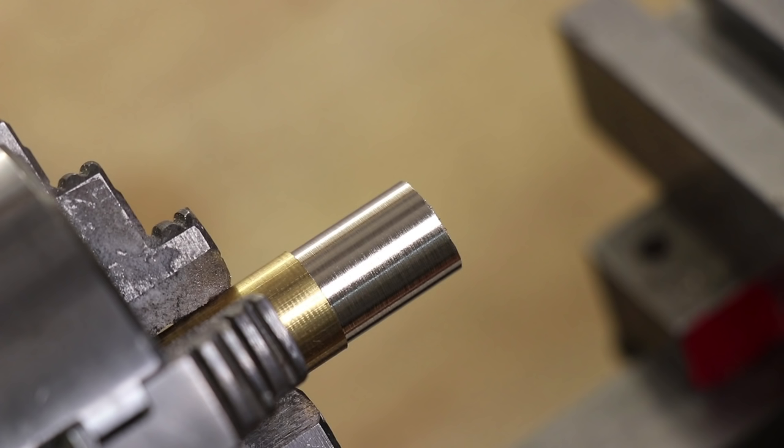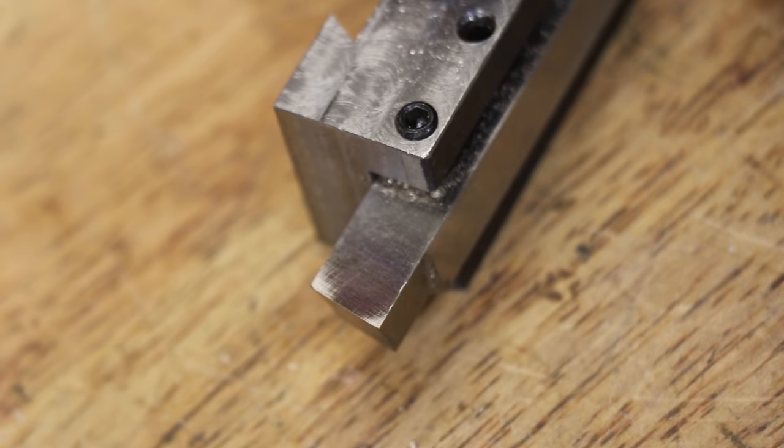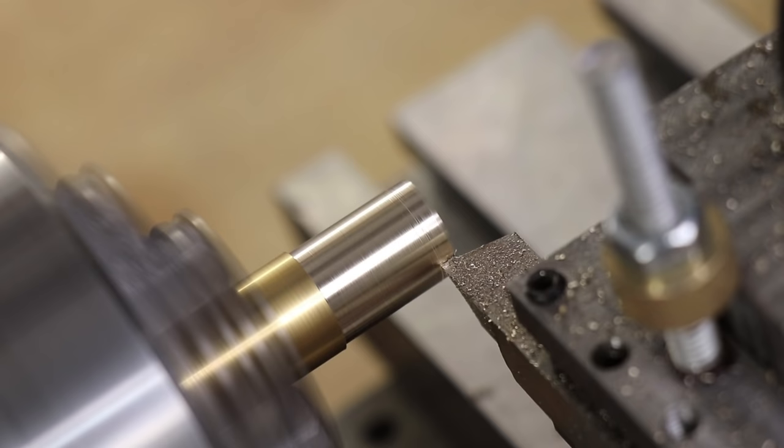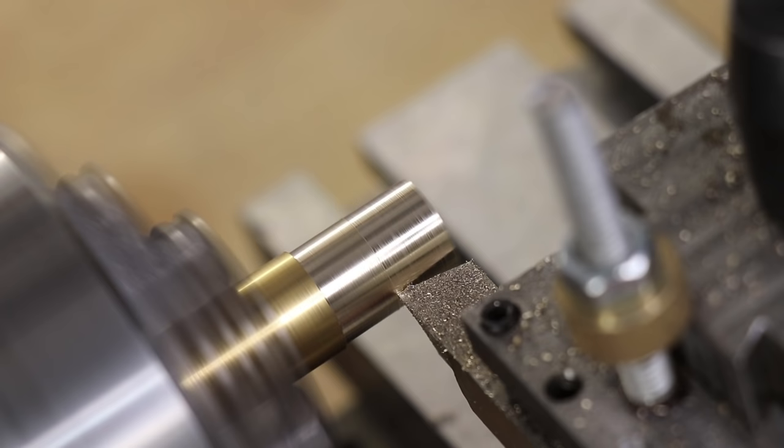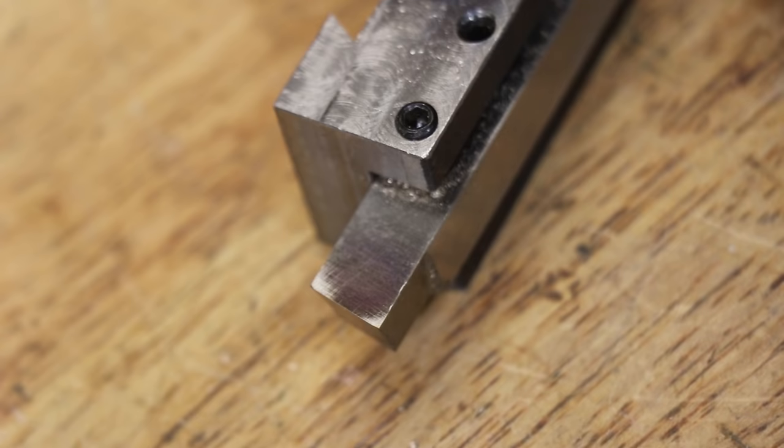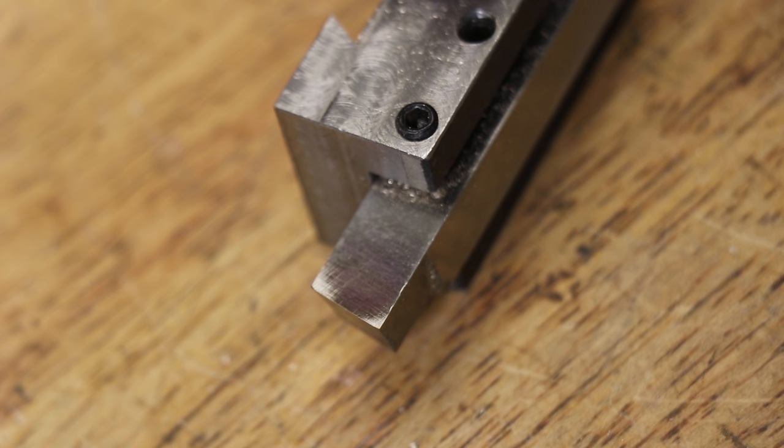I could have probably used a higher RPM, but the tool cut fine. What isn't fine though is the surface finish. I left the tool with a very sharp corner, which is great for getting into corners and taking very light cuts. For example, I'm taking a cut of 0.025 millimeters without much issue. But to get a good surface finish, I'd need to take a very low feed rate as well. As well as the poor surface finish, the small corner is not very strong. Take a heavy cut or use the wrong speed and feed and the corner will just burn off.